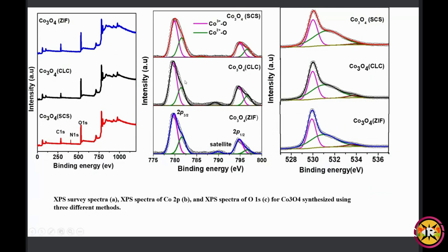Now coming to figure 2. Here I have done the cobalt 2p XPS, and after deconvolution, what I observed is a peak around 780 electron volt, which is cobalt 2p 3/2 3+, and around 782 is the cobalt 2+, and the peak around 794 is the cobalt 3+ 2p 1/2, and 796 is cobalt 2+ 2p 1/2, and around 790 one satellite peak arrived for cobalt 2p 3/2.